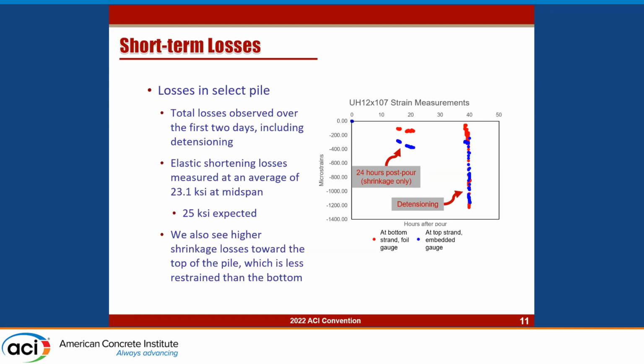And this graph shows just the times that we measured after pouring. So this first region was before we poured, where there's no strain in the system. And then 24 hours post-pour, where we are only getting shrinkage. And then the detensioning process, where we see a very swift increase in the compressive strains.